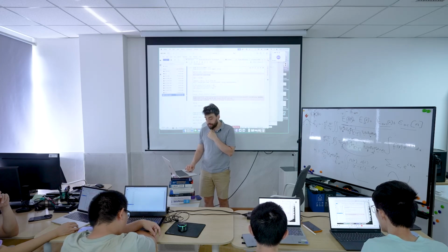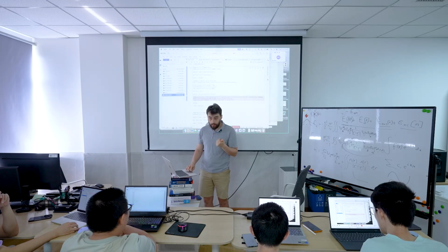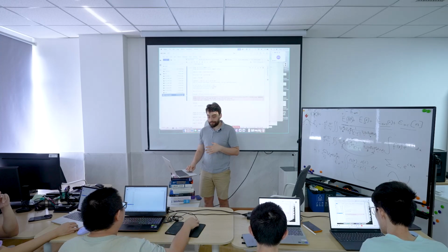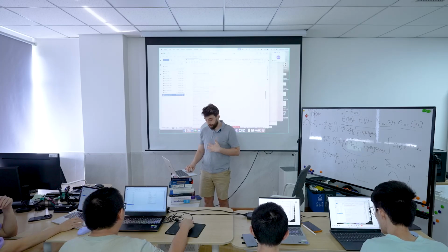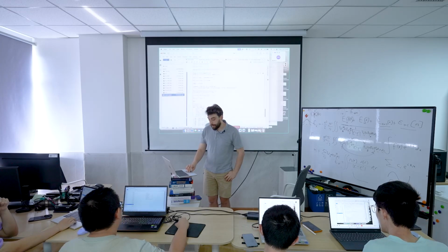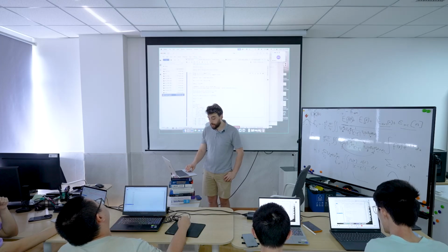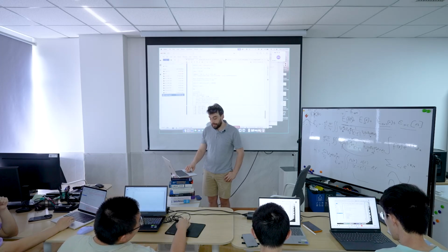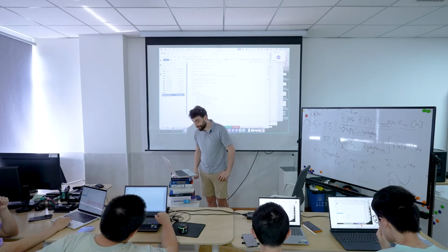So yesterday, as a recap, we did this calculation where we set up a bulk palladium FCC conventional cell, and we ran a basic CASTEP calculation. We ran LDA, we ran PBE, and we explored different basis set precisions. Basically different cutoff energies for our plane wave basis. And what we said was, we can set up one of these calculations which has a particular Brillouin zone sampling, K-point sampling, in this case 2 by 2 by 2, and we can loop over these cutoff energies.